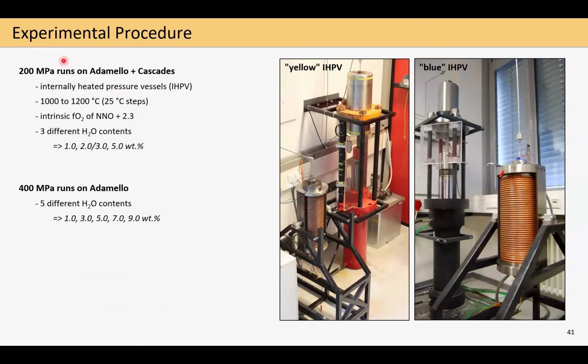I ran 200 megapascal experiments on both compositions at temperatures of around 1000 to 1200 degrees, with 3 different water contents for each starting material to investigate the effect of water on phase equilibria. And additionally, I did some 400 megapascal runs on the Adamello compositions, where I just expanded the range of water contents to higher levels to account for the higher solubility of water at higher pressures. And for this project, I used mainly these two IHPVs we have currently available in our lab.